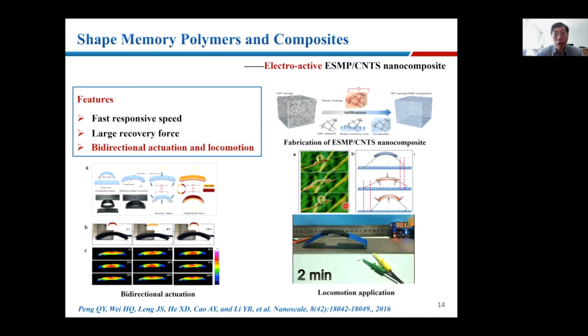So I take one example. This is the carbon nanotube sponge we make. The reason we make the sponge is that this one has very good conductivity in 3 dimensions. So we combine the carbon nanotube sponge with shape memory polymer epoxy and make a composite. Then this one has very good conductivity. We also can make this one a two-way shape memory polymer composite. So that means this one can do bidirectional actuation and locomotion.